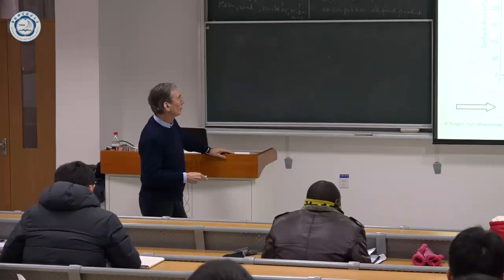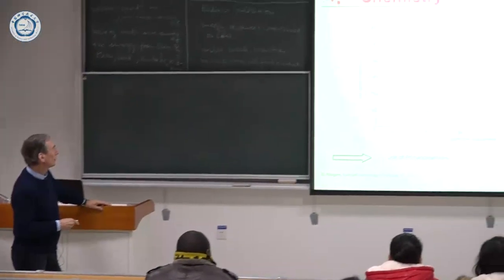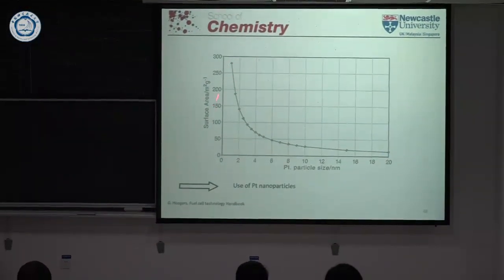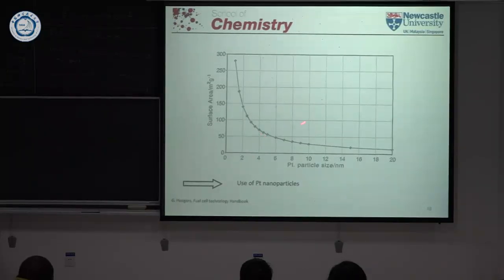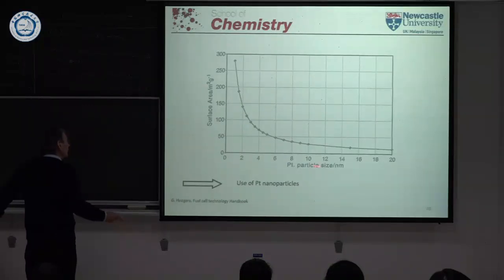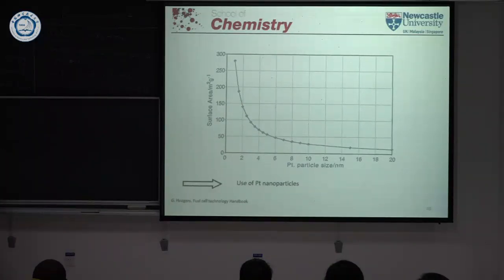And you see actually when you go from 20 nanometers down to about 2 or 1 nanometer, I see how steeply it increases the surface area. So a typical compromise between these two factors is to go to about anything between 2 and 4 nanometers. So this is the range that's typically used actually in a fuel cell. So you still have actually a fairly high surface area, but the stability is larger than if you would go actually here to these particles. And it's interesting to see that it's not a linear curve at all, but it's a very, very steep curve to the small particles. It's a 1 over R relationship. That's the reason that that looks like this.